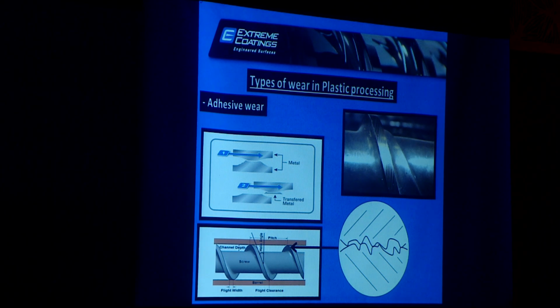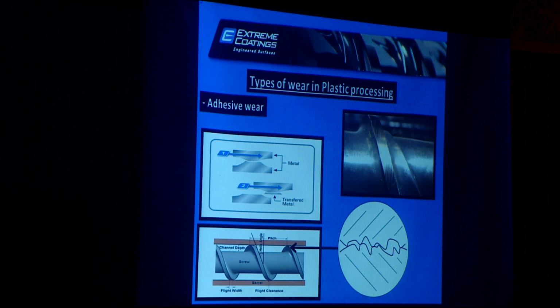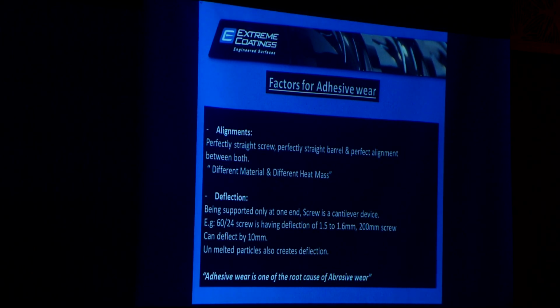Now, with our eyes we cannot see. We see that the screw and barrel surfaces are very smooth, but actually it is nothing but peaks and valleys. And two high points under tremendous shear come in contact with each other. It creates welds between each other, and because the screw is rotating, it ruptures the steel, whichever is the weaker one. And that's how the wear starts in your machines. There are many reasons for this. As I said, the alignment, the deflections and the cantilever kind of assembly, these are the reasons.